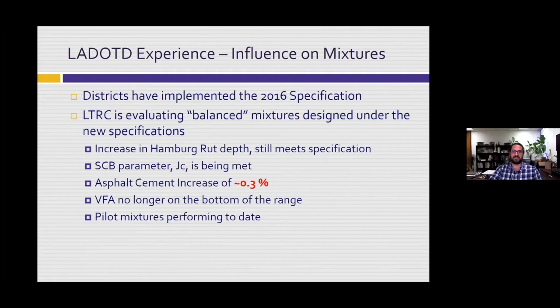Influence on the mixtures, we have seen a slight increase in the Hamburg rut depth, but I say that understanding that we were seeing mixtures produced with PG76-22 with a 2 millimeter rut. Now those mixtures are at a 4 millimeter rut. So it's not really a bad type of increase, but there is a little bit of an increase. It's still less than the specified limits. The SCB parameter is being consistently met. I've seen very few failures in the submitted JMFs.